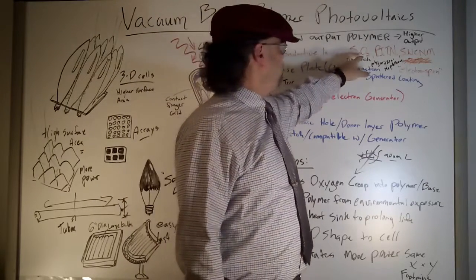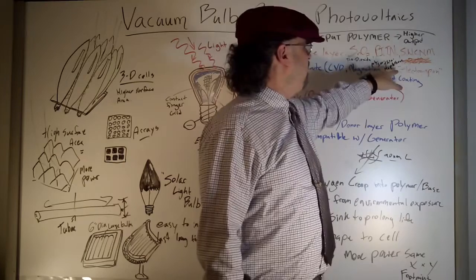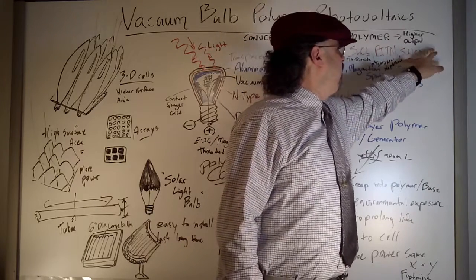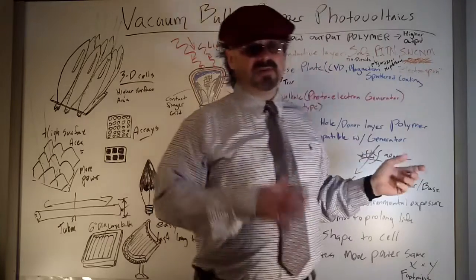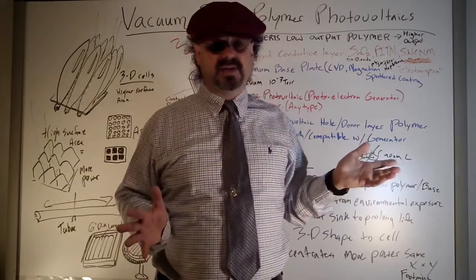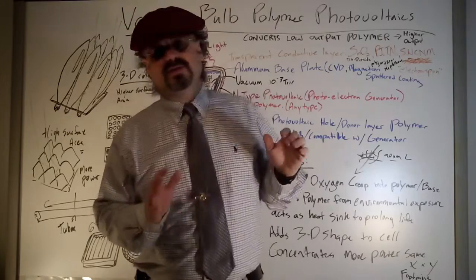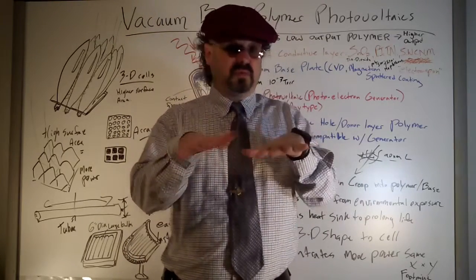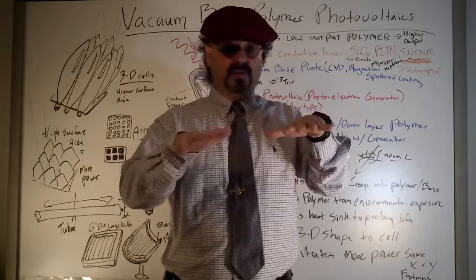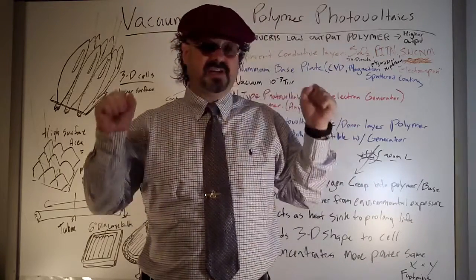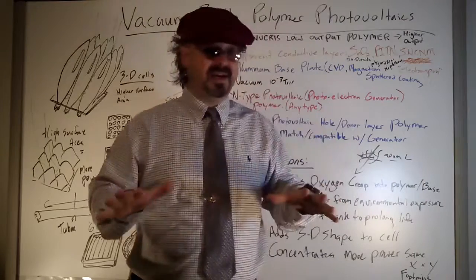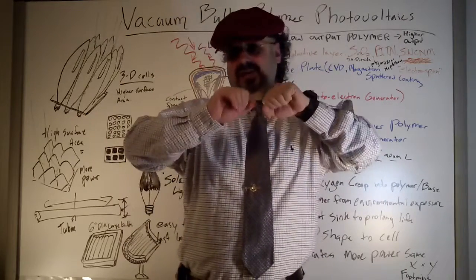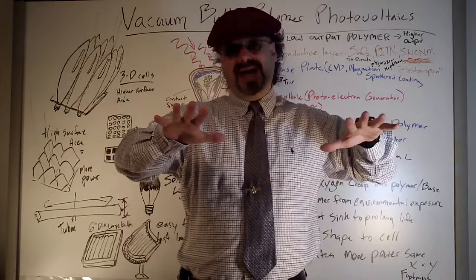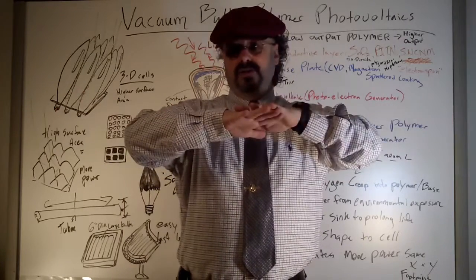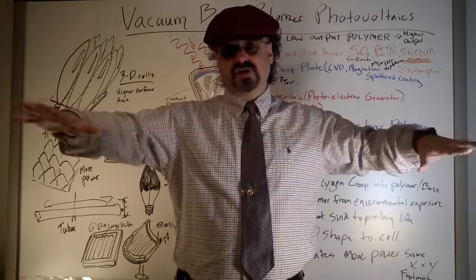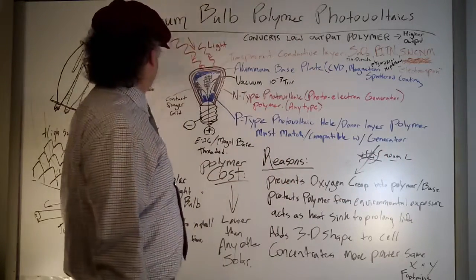Okay, so the transparent conductive layer, you've got to use a tin dioxide, polyisothianaphthene, or a single wall carbon nanotube mat, electrospun. And if you've ever dealt with electrospun carbon nanotube mats, there are certain processes you can use to essentially grow Brillo pad looking stuff of single wall carbon nanotubes, where it's all connected together. So you end up with extremely high thermal conductivity, extremely high electrical conductivity, and you can create a sparse enough mat to transfer that charge. And that's really important when you talk about large surface areas.